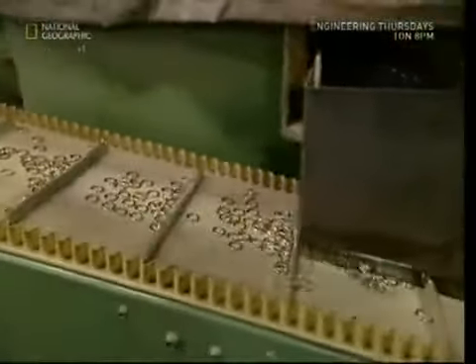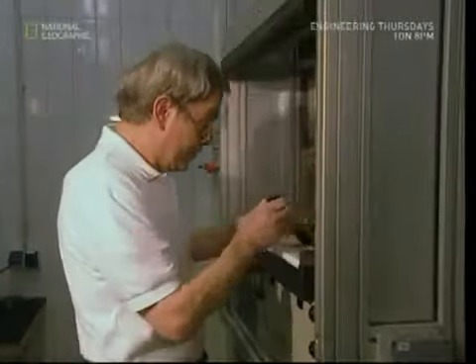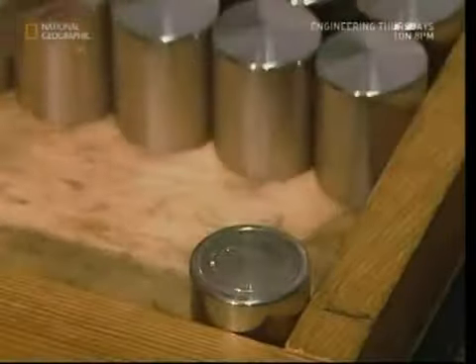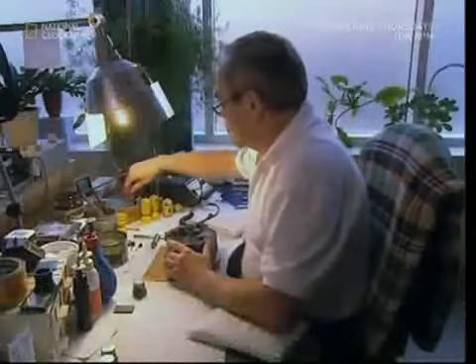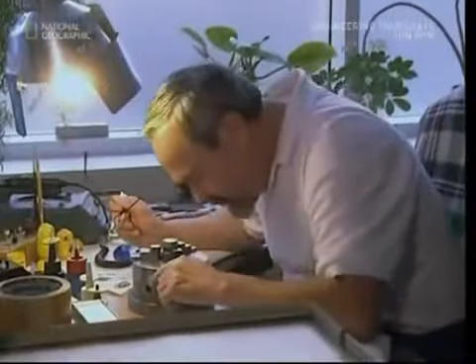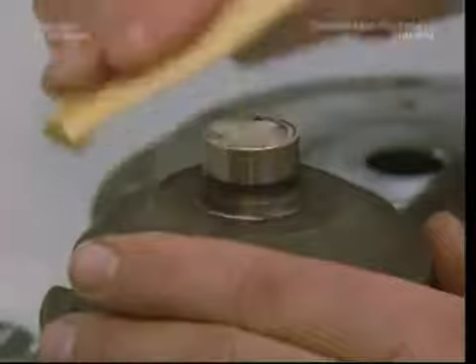We've got our outer rings and we've already made up the fillings, but there's still something missing — all of our pieces are blank bits of metal. A template is needed to turn them into coins. The engraver's job is to make the coin equivalent of a rubber stamp, which permanently marks the value onto the coin. Using an industrial press, he crushes a pattern onto the stamp block, exerting 160 tons of pressure, so he's got to be very careful. The stamps are hardened in a furnace at 870 degrees Celsius. Without this treatment the motif would disappear very quickly, but once it's been hardened, each stamp can engrave as many as 200,000 coins. The surfaces are scraped clean using fine glass to remove any imperfections, then checked and polished before being put to work.